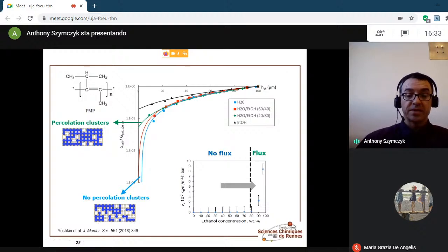Indeed, it can be seen in this figure, in which the conductance is represented in the logarithmic scale, that the electrical conductance in the membrane matrix is almost zero as long as the threshold concentration of ethanol is not reached in the mixture. Above this threshold value, the electrical conductance of the membrane matrix becomes significant, indicating the connection of the liquid clusters in the membrane and the formation of the percolation clusters, allowing the transport of liquid under pressure.